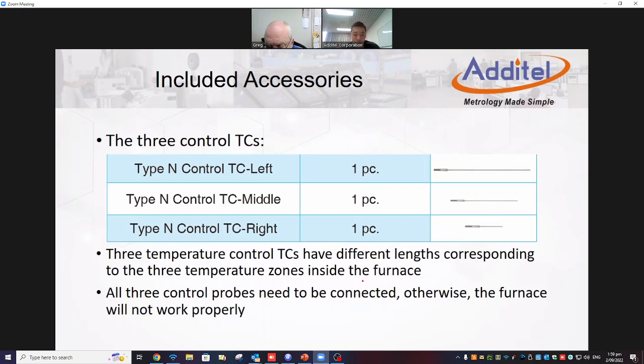Although when we do the temperature testing, we control the accuracy of the thermocouple to only 1 degree Celsius, when you combine 3 together, after the algorithm and the combination of the readings, the temperature accuracy is better than a single thermocouple. And also after transportation or long-time use, the accuracy of the display number will be 5 degrees Celsius. So that's pretty huge. Normally, you should not use that as a reference number.